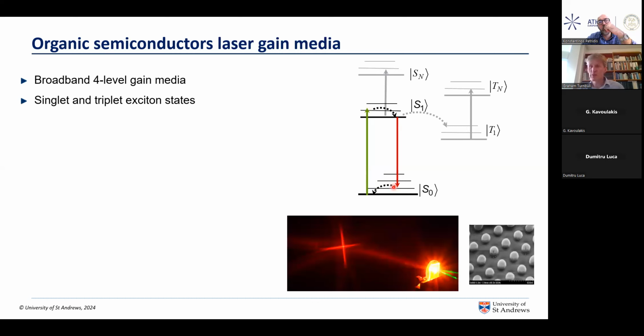Organic semiconductors, however, also have a manifold of both singlet and triplet exciton states, and the triplets normally cause problems. They're troublesome triplets because they will not emit light, but they will absorb light very often at the wavelength you're trying to amplify.